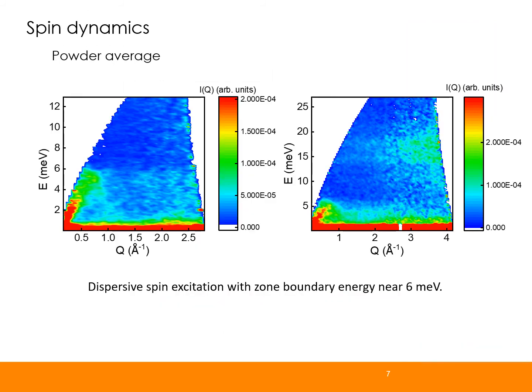Before showing you the inelastic data, let me show you the powder average spin excitation spectrum, which I measured at CNCS, SNS, Oak Ridge National Laboratory. From the powder average data, we can see that the spin excitation spectrum has a zone boundary energy around 6 meV. The zone center looks close to Q equal to 0, but because of the resolution limitation of the instrument, we are not able to look into the dynamics at Q equal to 0.